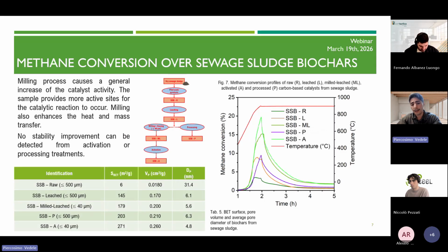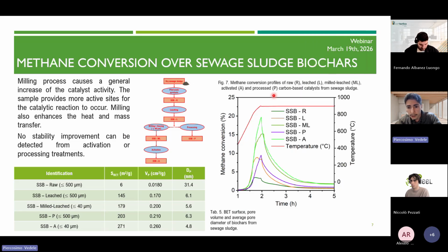As you can see, the activation of the milled-leached char allows us to get a slightly higher conversion and the same steady state conversion. Let me use the pointer here. Okay. A slightly higher conversion compared to that of the milled-leached and the same steady state. The pretreatment of the leached char instead allows us to get a conversion which is comparable to that of the leached char and more or less the same steady state. So for this reason, no stability improvement can be detected from the processing treatments.